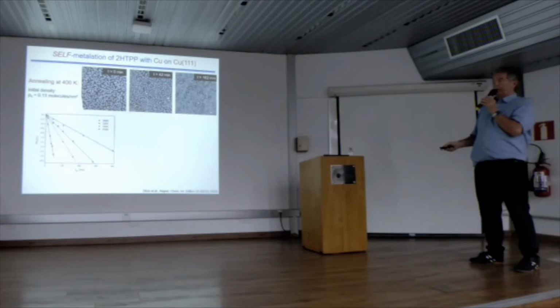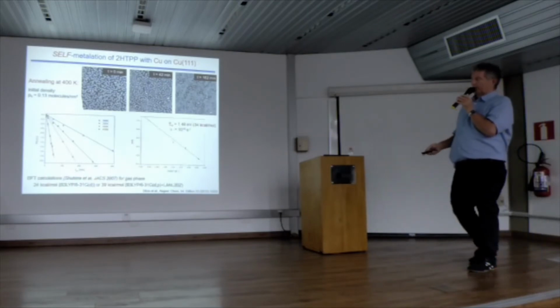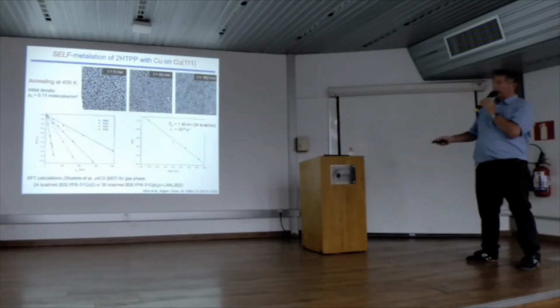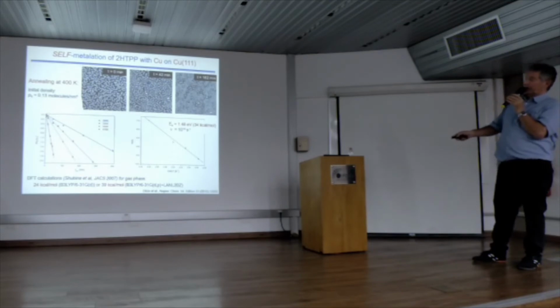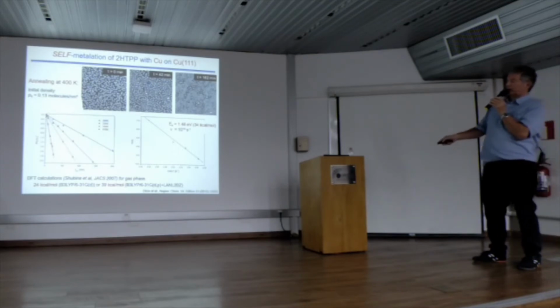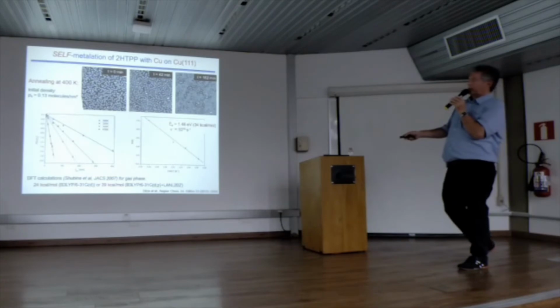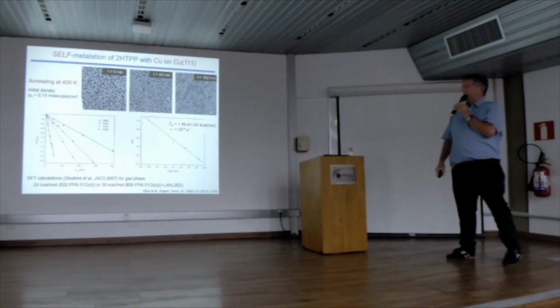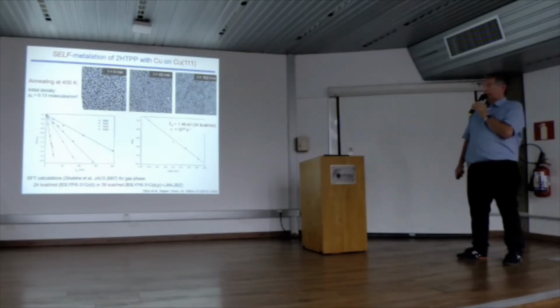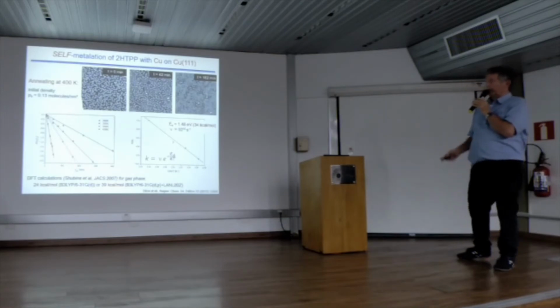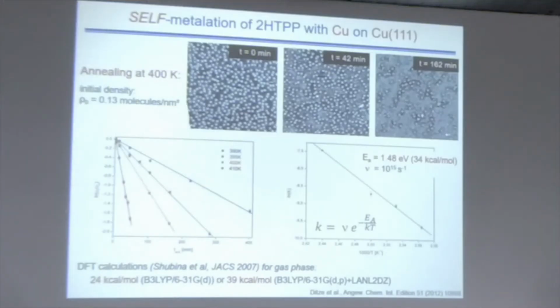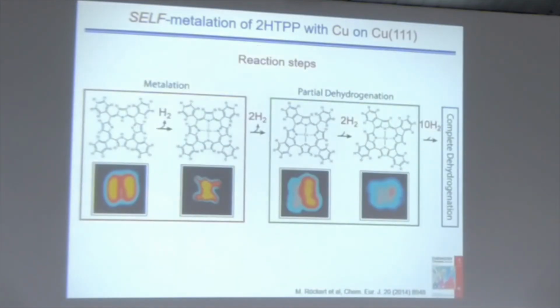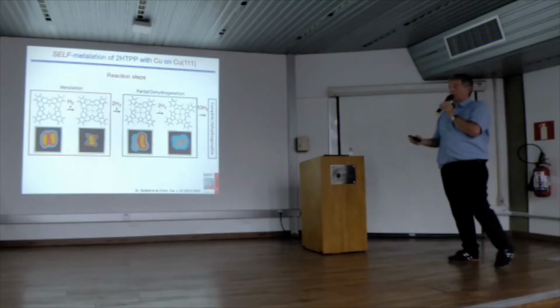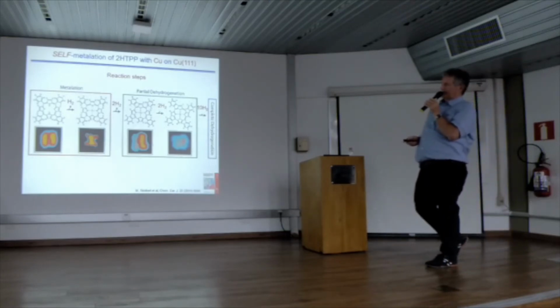And then we do an Arrhenius analysis of these slopes. And this is shown here, the Arrhenius analysis of the slope, so ln k versus 1 over T, and we get the activation energy for this reaction: 1.48 electron volt. Yeah, this is the Arrhenius equation for those who have forgotten it. And we can even follow this reaction in a little more detail with STM.